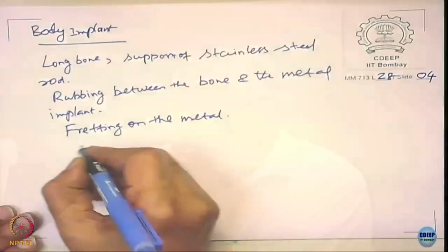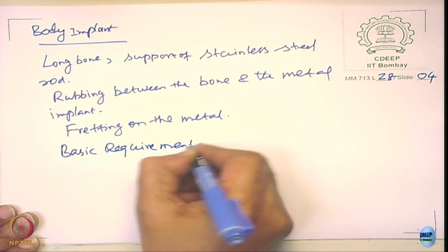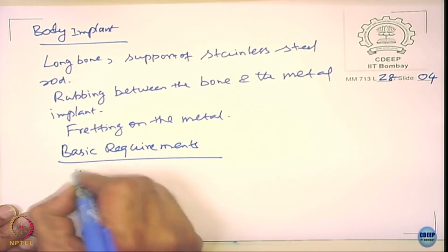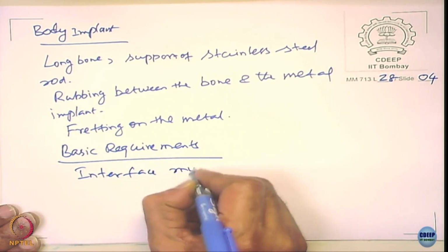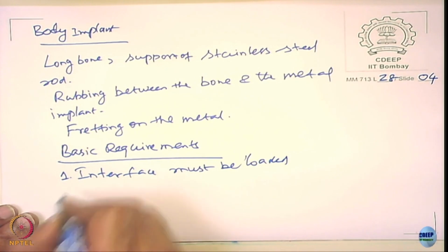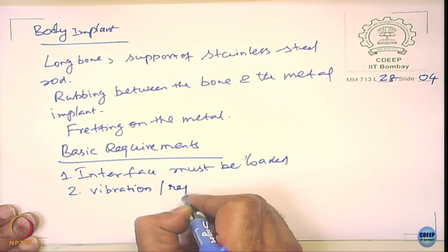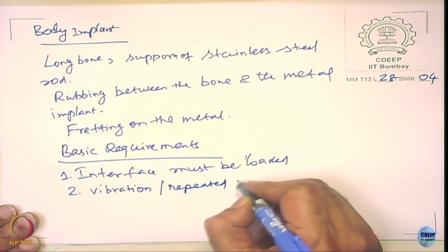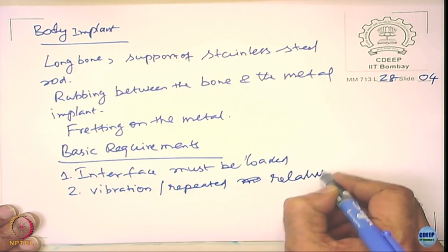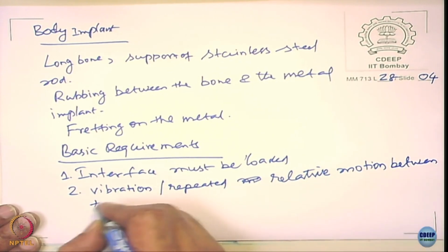So, there are 3 basic requirements. The basic requirements are: the interface must be loaded; there has to be vibration or repeated relative motion between contacting surfaces.